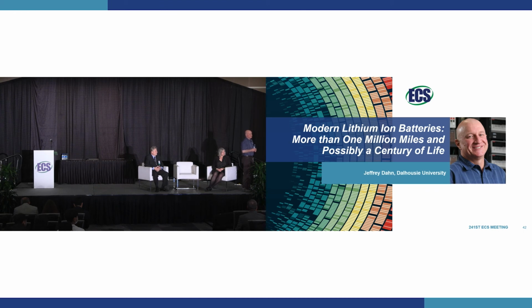Yeah, I understand the question. So you have to realize that in both systems, you're using the same graphite, and in both systems, you're exercising the graphite 100%. The graphite is being completely filled, and the graphite's being completely emptied in both systems. And in both systems, the degradation mechanism is loss of lithium inventory at the negative side, okay? And by limiting the voltage to 3.8 volts of the NMC system, all that other lithium, we never touch it. We never touch it, right? So you say there's extra lithium, but I say, fine, but we never touch it. We don't use it.